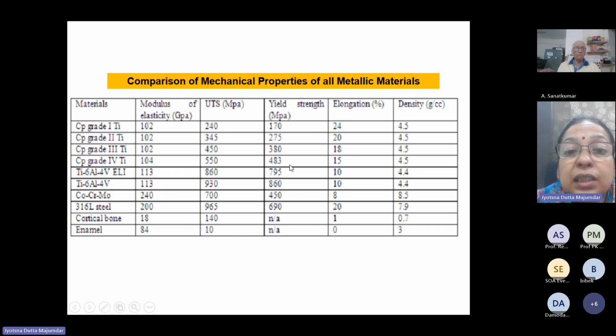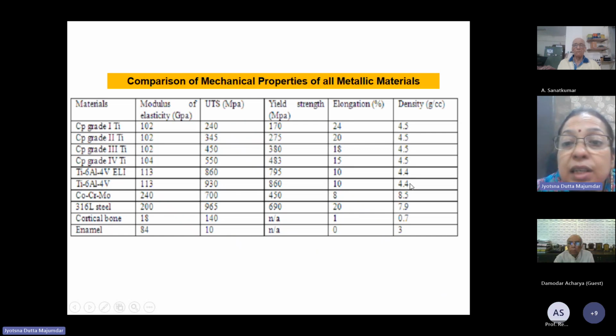But on the other hand, if you talk about strength and percentage elongation, titanium and steel are of a similar category. I mean, they perform at the same level. However, if you talk about density, it is much higher for steel and chromium molybdenum alloy as compared to that of titanium and its alloys.